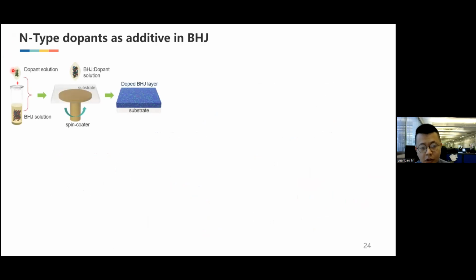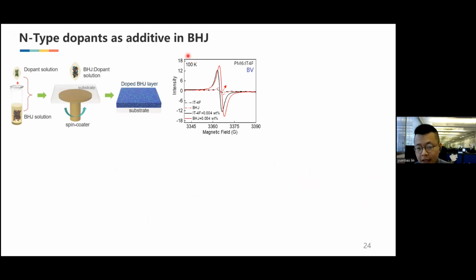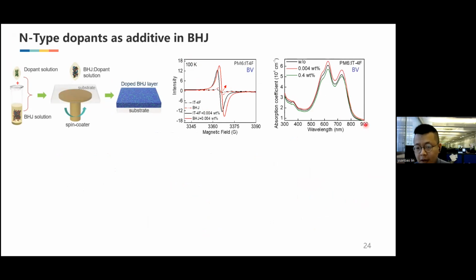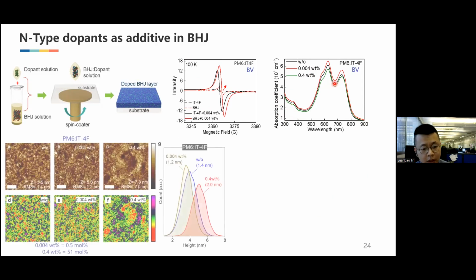We tried adding this dopant in the bulk heterojunction, and after spin coating, we detected an enhanced EPR signal compared to the one without dopant. We also measured the absorption after doping. With low doping, the absorption coefficient can increase a lot, but if we put in too much dopant, the absorption coefficient will reduce. Also, this n-type dopant acts as a morphology modifier.